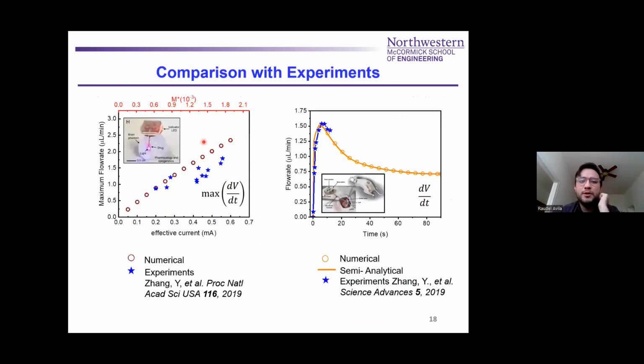So if we compare it with some of the experiments on the device that I showed you before, this is for the delivery of the drug in the brain, we can quantify the maximum flow rate. So this is going to be the peak here on the flow rate versus time curve. And we can see that for effective currents that range from about 0.1 to 0.6 milliamps, the prediction for the maximum flow rate is okay. It's good actually at the small range of the currents, but for larger currents, you might have some additional bubble generation that might affect the effective current that's going into the device. So we end up over predicting a little bit in the numerical aspect, by a few percent.